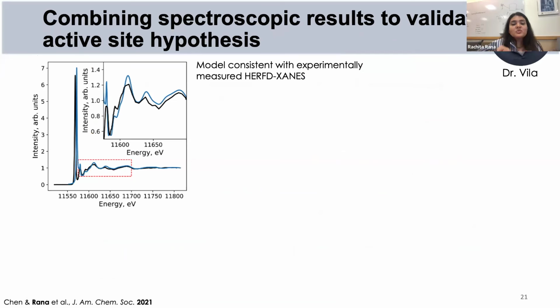So this was one thing. From EXAFS, using QuantEXAFS, we had an answer to our puzzle as to what structure our catalytic site could best match. And then because we had done other spectroscopic measurements on this material, we went to SLAC to do HERFD experiments, and we collaborated with Fernando. I gave him the structure that we figured from QuantEXAFS, and he helped us do simulations of the structure. And indeed, the structure that we found from QuantEXAFS that gave us the best EXAFS fit was the one that gave us the most reasonable fit for HERFD as well.